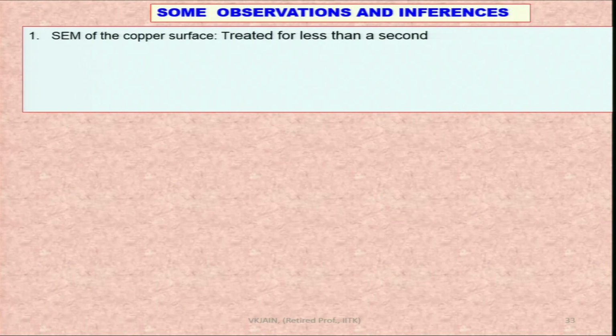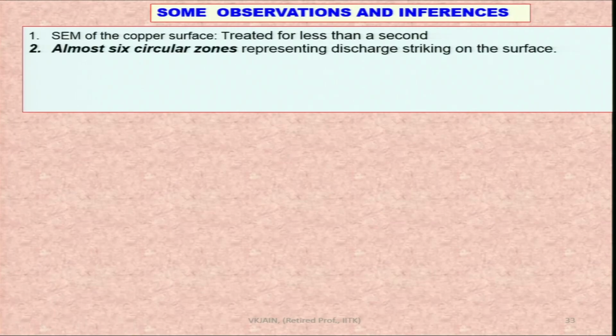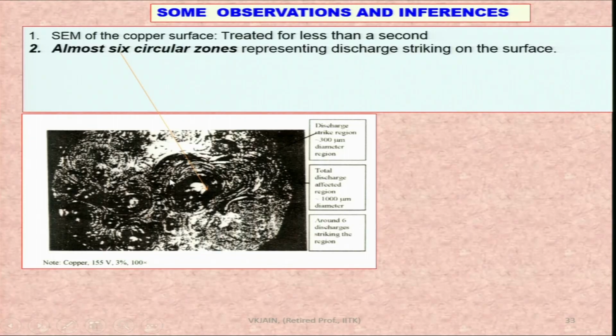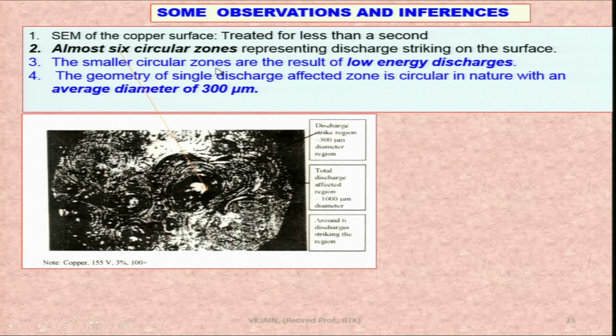SEM of the copper surface treated for less than a second, almost 6 circular zones representing discharge striking on the surface. You can see here, these are the different circular zones due to the sparking taking place. The smaller circular zones are the result of low energy discharges, and the geometry of a single discharge affected zone is circular in nature with an average diameter of 300 micrometer.